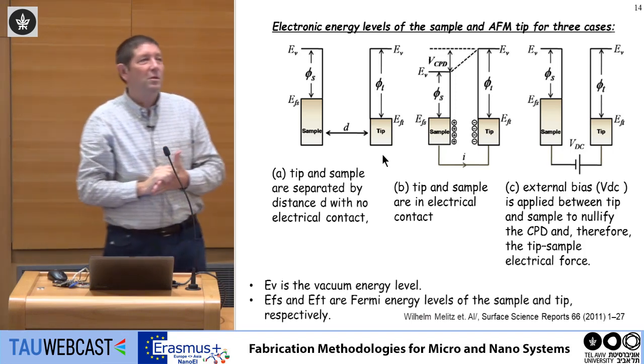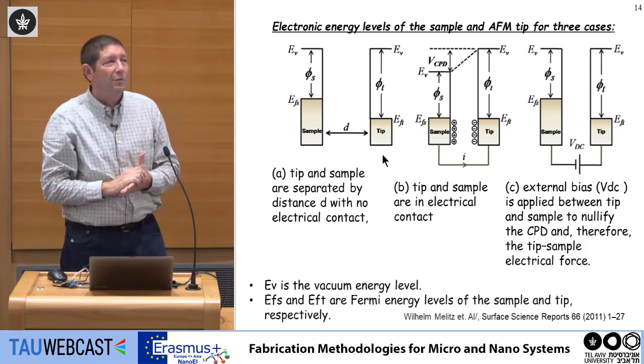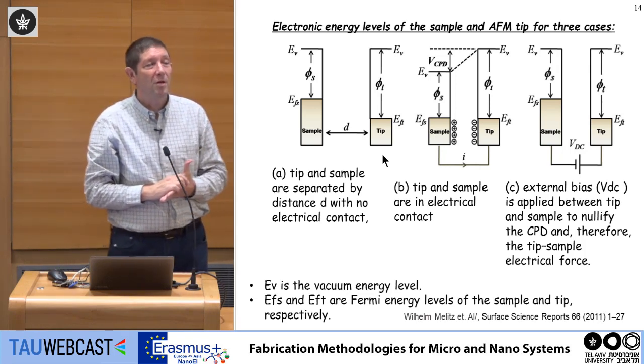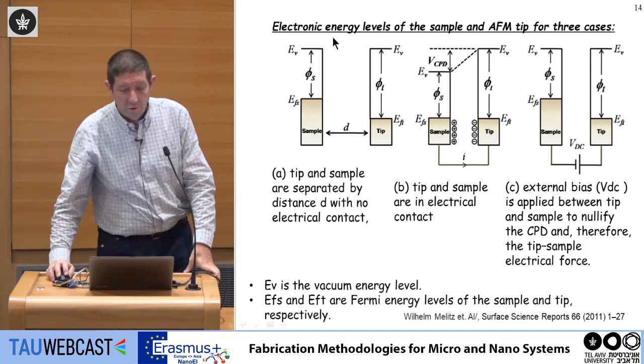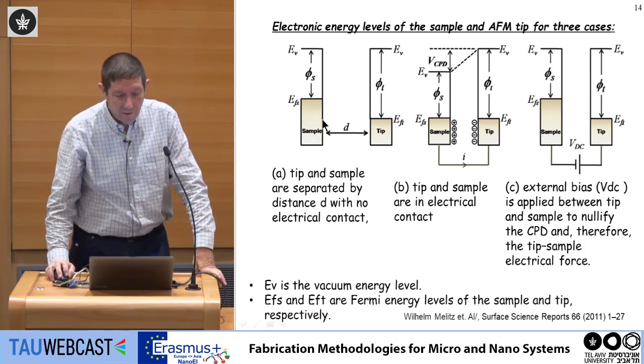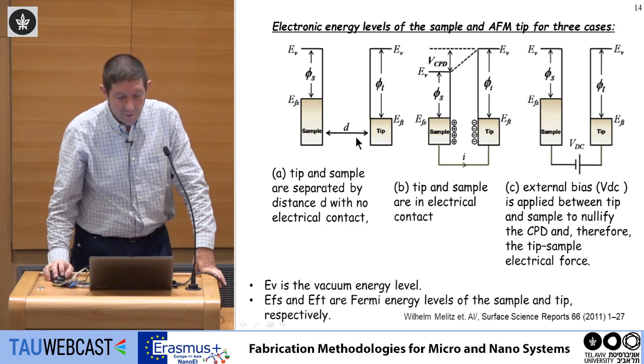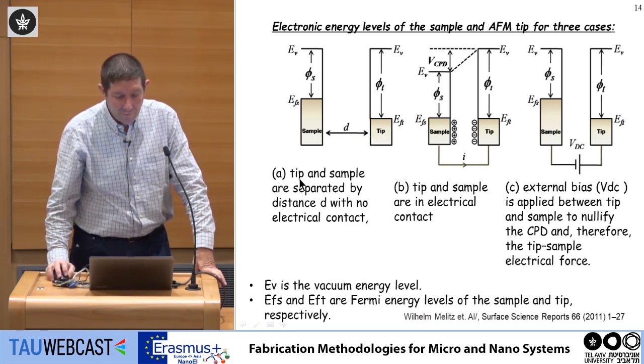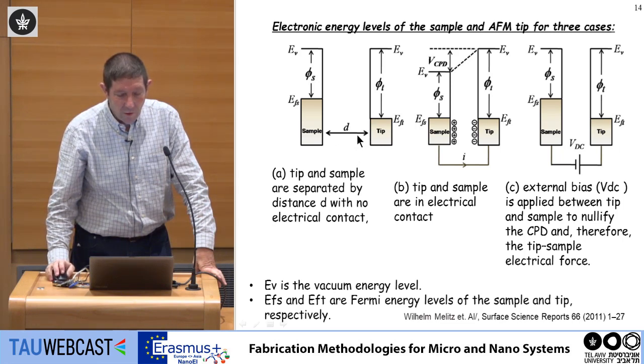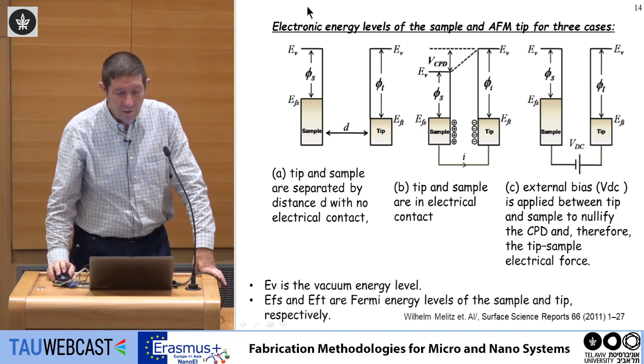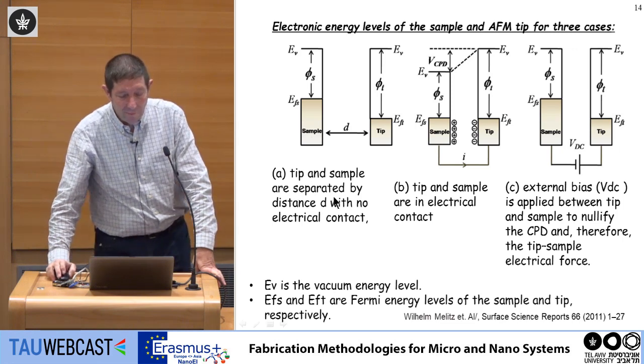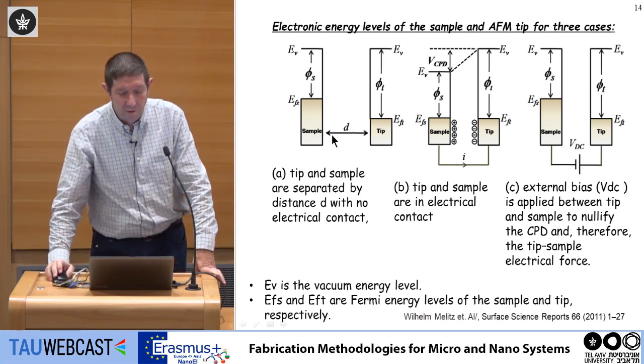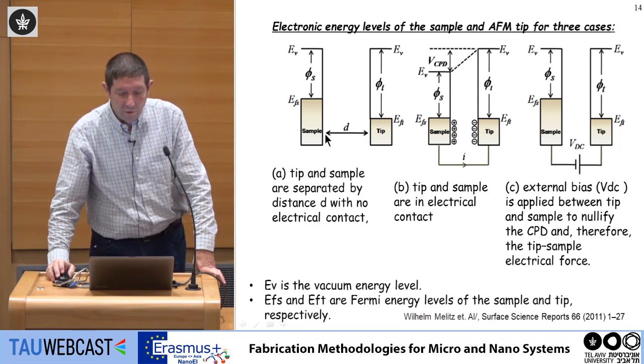But you can also use this technique to look at Fermi level, look at charge. You can use it to measure change in potential. So electronically, if you are thinking about the tip as a material and the sample as a material, this is the tip, this is the sample, and this is a solid, this is a solid. So you can look at the electronic level of the sample and the AFM tip for 3 cases. First one, tip and sample are separated by distance d with no electrical contact. Then the next step, you are connecting them. The tip and sample are in electrical contact.